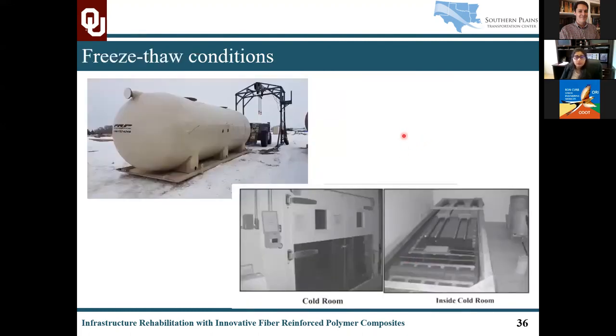Considering freeze-thaw conditions, this is one of the primary types of environmental stress that seriously threatens the service life of concrete structures in cold regions. And when FRP composites are used in civil engineering structures, the properties of FRP composites and the bond capacity between FRP and concrete may be degraded with increasing freeze-thaw cycles. So it's very, very important to understand these behaviors in the extreme conditions of a freeze-thaw. So currently, our team at OU is working on investigating the freeze-thaw behavior of FRP with traditional conventional FRP and also nano-modified resins incorporated for FRP, and how this behavior affects the durability.